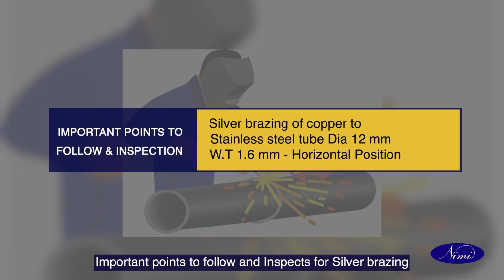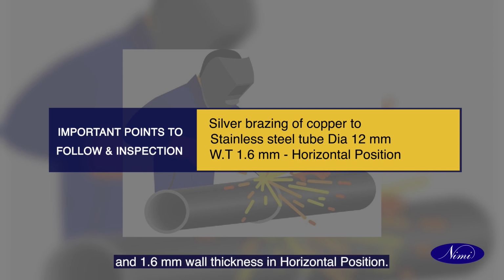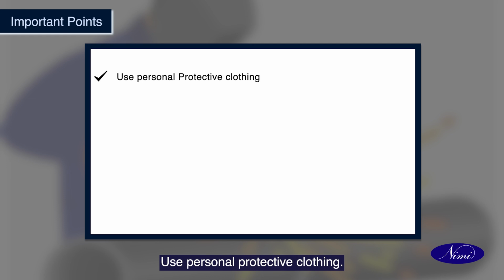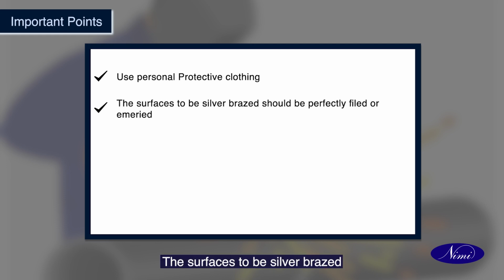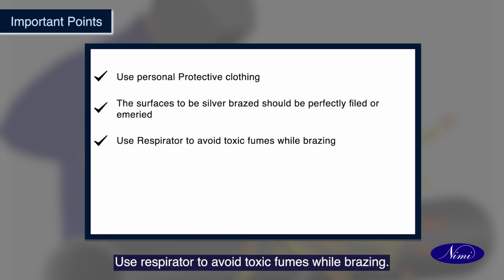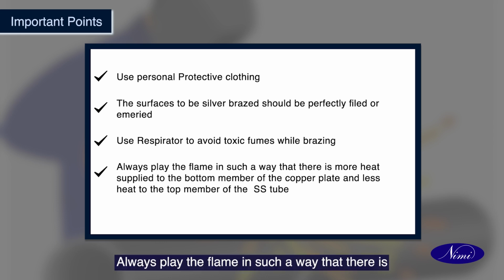Important points to follow and inspect for silver brazing of copper to stainless steel tube, diameter 12 mm and 1.6 mm wall thickness in horizontal position. Use personal protective clothing. The surfaces to be silver brazed should be perfectly filed or emeried. Use respirator to avoid toxic fumes while brazing. Always play the flame in such a way that there is more heat supplied to the bottom member of the copper plate and less heat to the top member of the SS tube.